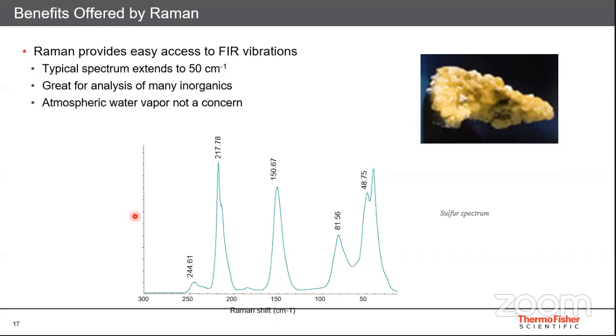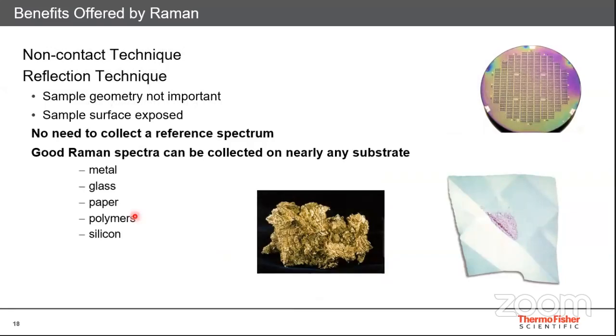So it's a very good tool for inorganic molecules, which we see absorption in the far IR region. Many of the inorganic compounds absorb nicely in the Raman spectrum. And atmospheric water vapor is a concern in infrared spectroscopy. That's why you have to take the background. But something which is strongly IR absorbing, well, there's no problem for Raman. So atmospheric water vapor is not a problem for the Raman, because water absorbs very little in Raman spectroscopy.